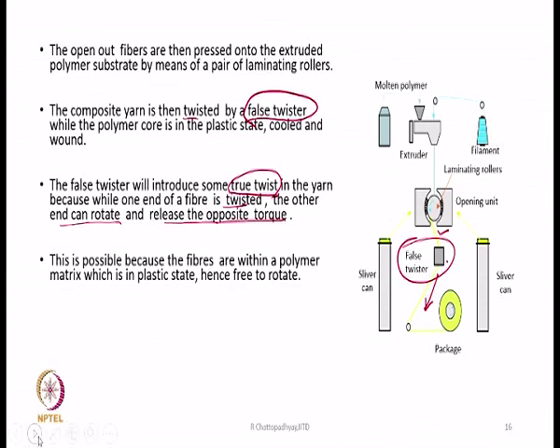This is possible because, as I have written here, the fibers within the polymer matrix, which is in a plastic state, are free to rotate. So, there is the trailing end of the fiber bundle which is getting false twisted. The trailing part is within the polymer matrix which is in a molten state, and therefore, the fiber ends have some freedom to rotate because the torque is present there, and hence some true twist will be seen in the final yarn.